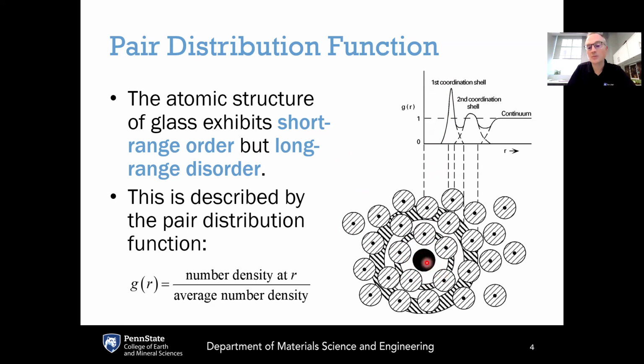There's probably also a preferred coordination number, which would be the number of atoms that you have in this first nearest neighbor shell. There might also be preferred bond angles there. But this pair distribution function is capturing the preference for the distance, the bonding distance between the central atom and the first nearest neighbor. So the first peak that you see in the pair distribution function occurs at the most favorable bond distance between the central atom and its first nearest neighbor.